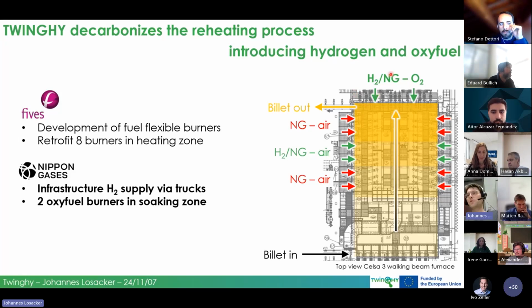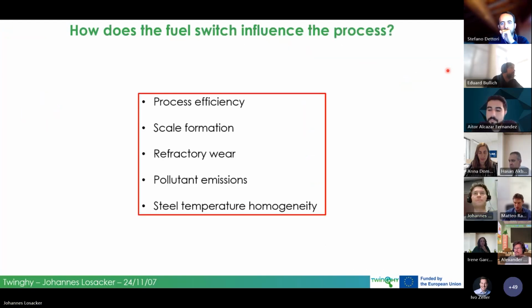And the nice thing, besides the fuel flexibility again here, is that they use oxy-fuel. So they use oxygen, pure oxygen, instead of air for combustion, which essentially makes the process more efficient because you don't have to heat up all the nitrogen that's contained in the air. So the flame, the combustion itself, the flue gases are actually gaining temperature from that, and this in turn promotes the heat transfer to the product. The only drawback, of course, is that oxygen has some certain price, while air is basically for free. So this is the one pathway, the actual retrofit of this furnace.